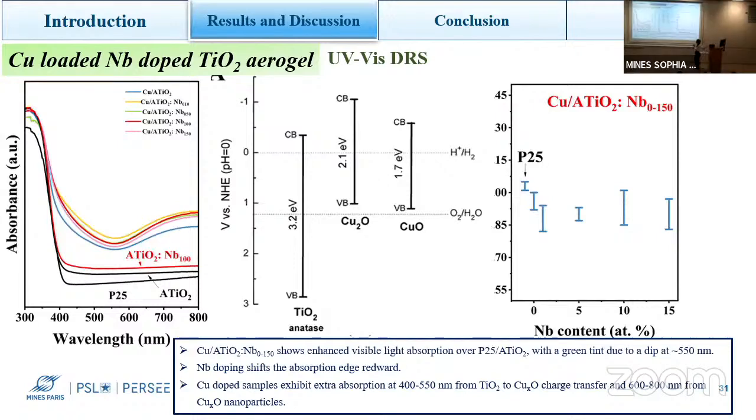Maybe from the ammonia treatment, there could be some copper zero generated. Yeah, but from XPS, I should do the LMM, should do that to see if there is copper zero. But I skipped that part. I just looked at XPS from copper 2p directly, only checking copper 1 and copper 2. I didn't take care of whether there is copper zero.